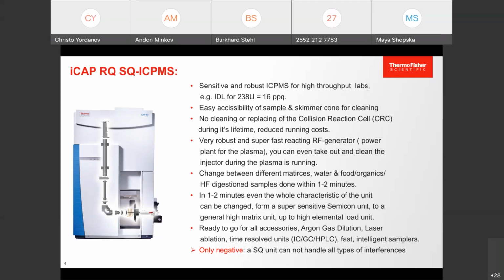This can be done within 1 or 2 minutes, including even stabilization time. Vacuum, of course, is not broken by this exercise. Also, you can change the normal characteristics, so a high matrix ICP-MS into high resolution ICP-MS, let me say in brackets. With changing the inner orifice, you can have this characteristic of a semicon unit. Means highly sensitive, but of course you sacrifice a little bit matrix tolerance.